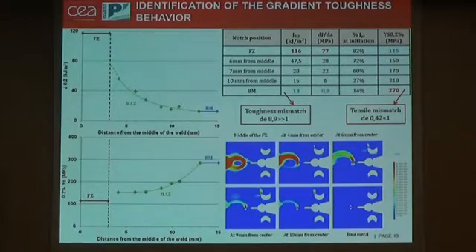These correlations were developed for the different tests, and finally a model that predicts the J integral at 200 micrometers of crack extension is developed. Unlike tensile tests where the fusion zone exhibits the lowest strength, the integral J is enhanced and the toughness is enhanced in the fusion zone, with approximately 8 times higher value than the base metal. We have 116 kJ per square meter for the fusion zone and 13 kJ per square meter for the base metal. And here we have the extent of plasticity that denotes the high undermatch between the fusion zone and the base metal that we present here.